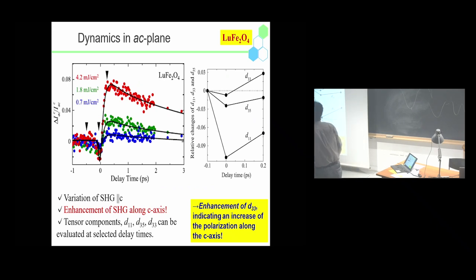The important result is the dynamics along the c-axis. By using the ac plane, we measured the time dependence of the relative change of the SHG along the c-axis. Just after photoirradiation, the c-axis polarized SHG shows a small drop. However, after that, the SHG increases from here to here by 8%. After that, such an increase gradually decreases from here to here. So we observe the enhancement of the SHG along the c-axis.